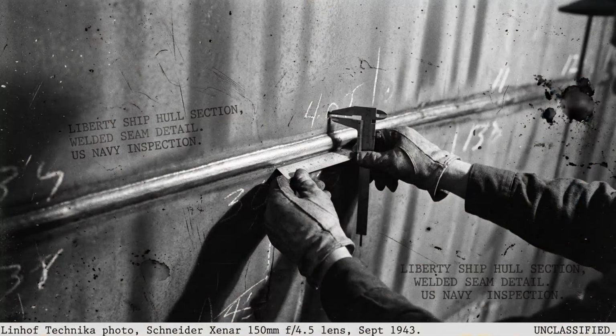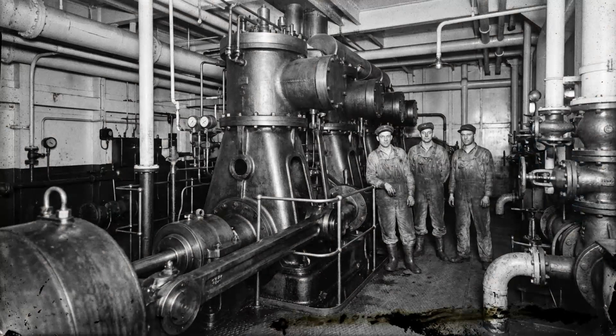The square corners of cargo hatches created points where stress accumulated, and these points often coincided with welded seams. When the temperature dropped low enough to make the steel brittle, cracks would nucleate at these stress concentrators and then race through the continuous welded structure at terrifying speed. Sailors reported hearing loud banging sounds as the cracks propagated, each bang representing the failure of another section of hull. In some cases, the entire process took only seconds, leaving crews no time to react.